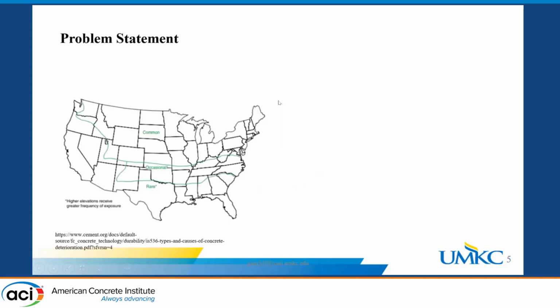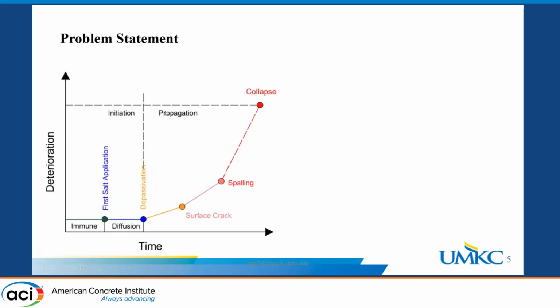If we look at the American map, we can see that in the northern states, for each storm event, we are using de-icing or anti-icing salt. Not all of the salt contains chloride, but those containing chloride are more effective and economic, in other words, cheap. On the other hand, on the East Coast and West Coast and some southern states, the reinforced concrete structures have direct contact with marine water, which contains a decent amount of chloride.